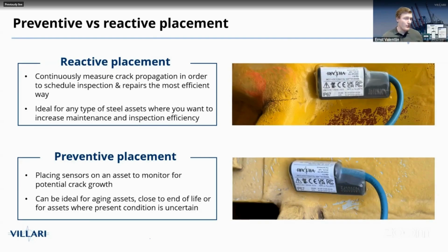For example, if you have a big steel bridge, there's likely going to be a lot of repetitive details that occur multiple times on a bridge. If at one point in time a crack has occurred in one of those details, it might be chosen to put strips on all of those details just to be able to detect it if the cracks also start to